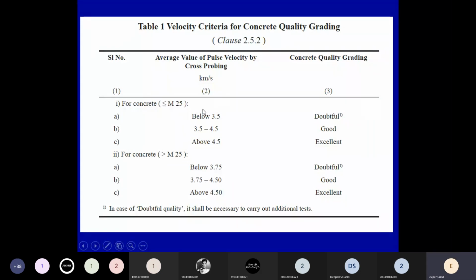So if anything is coming in the doubtful category, it indicates that there is some kind of voids, honeycombing or crack possibility inside your member. So for that, you need to carry out additional tests. It can be a concrete core test where we can drill a core at the location where we are getting the lower UPV values. So further investigation is recommended for values below 3.5 if your concrete is up to M25. If it is greater than M25, below 3.75 is doubtful, so further investigation needs to be done.